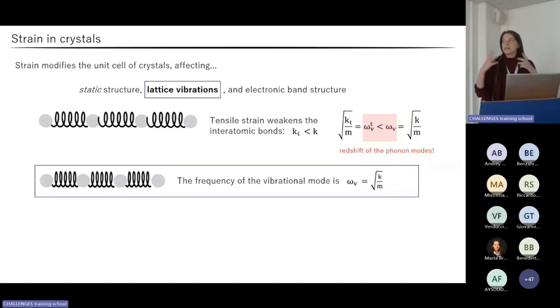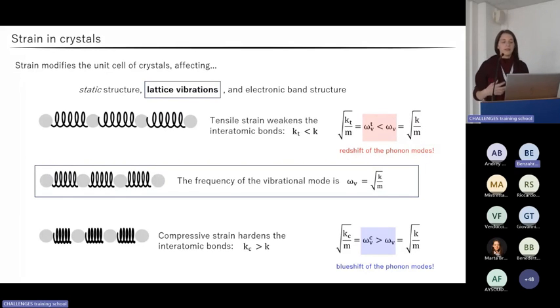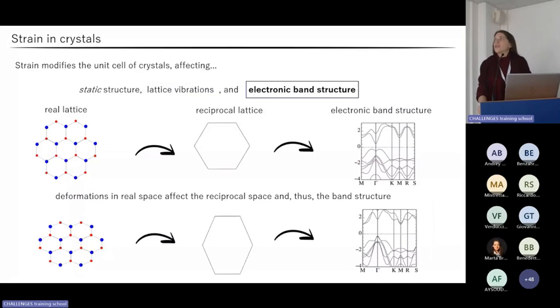In that situation, the elastic constant of our imaginary springs gets smaller and the frequency of the vibrational mode reduces, or redshifts. Conversely, when we apply a compressive strain, the interatomic distances reduce and the interatomic interactions increase. In that situation, the elastic constant of our system gets larger and the frequency of the vibrational mode increases, or blueshifts. Besides the structure-related properties, the application of strain on crystals also modifies the electronic properties.